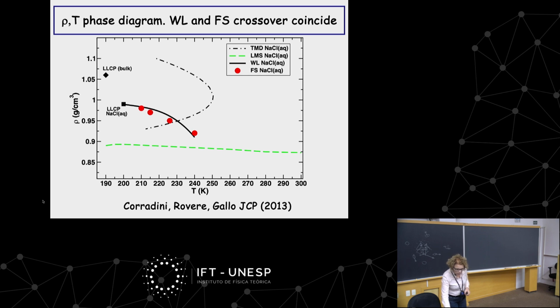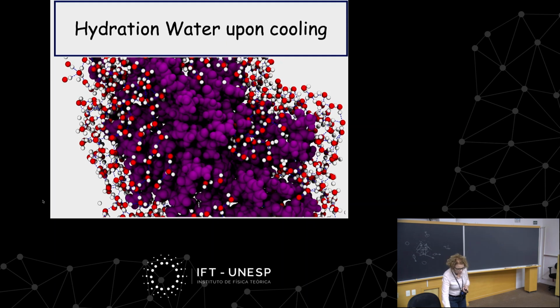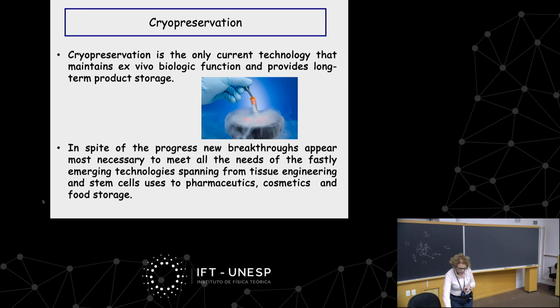So I don't have time to talk about the hydration water. Just let me tell you, and then this is my last thing, we studied also hydration water over cooling. This has to do with cryopreservation. You have to avoid freezing when you want to preserve organs, for example, or also stem cells. It's important to avoid freezing. And for doing that, since water has this strong tendency to crystallize, you put stuff in water. You put, for example, dimethyl sulfoxide, which is very cytotoxic but very effective. But since it is very cytotoxic, in order to diminish the quantity of dimethyl sulfoxide, people use disaccharides, carbohydrates, maximum disaccharides in general.